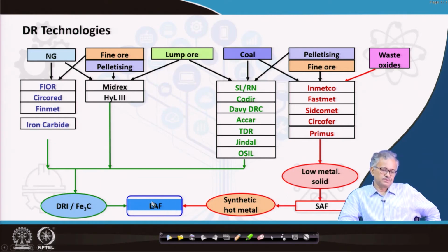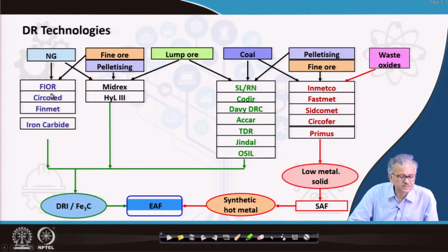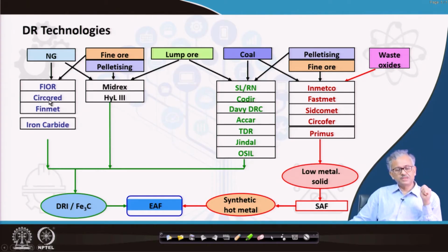It is similar to the hot metal composition, and finally you can purify this hot metal in the electric arc furnace. There is also the coal based rotary kiln process, and the product of the shaft furnace, the product of the fluidized bed, everything you can take to the electric arc furnace and melt it. In most cases, the fluidized bed product is briquetted, and then put into the electric arc furnace. And one major difference between the Finmet and the Circored process is that in the case of the Circored process,